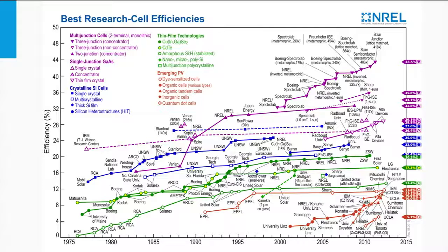The purple colored markers represent the III-V technology based on single, double and triple junctions and have efficiencies ranging from 26% up to 44% under concentrated light conditions. The blue lines and dots represent crystalline silicon technology based on monocrystalline and multicrystalline silicon. The record efficiency ranges from 20 up to 25% under standard one-sun illumination conditions, and 27% can be achieved under 92 suns illumination.